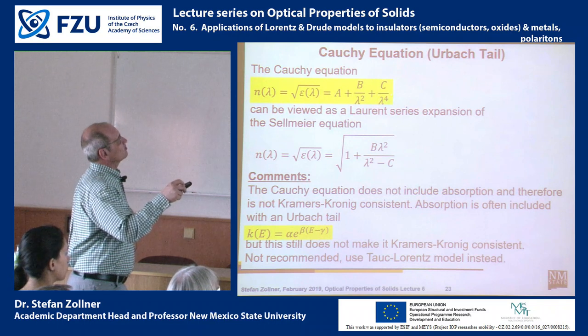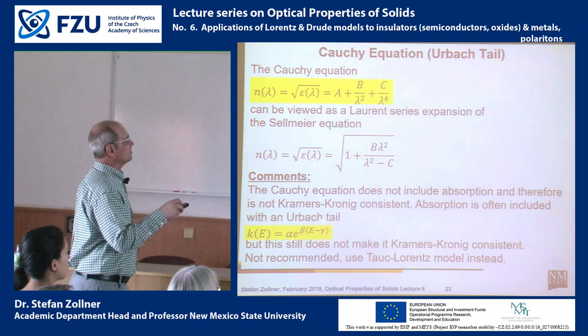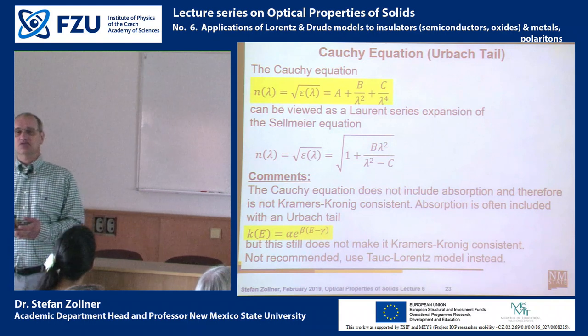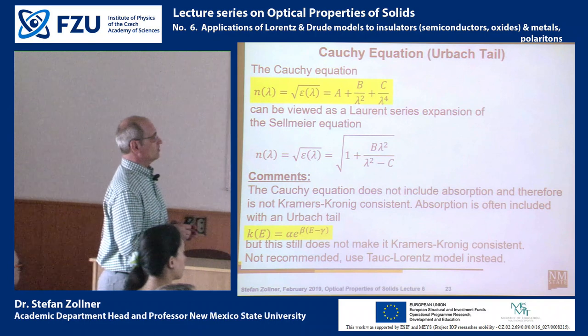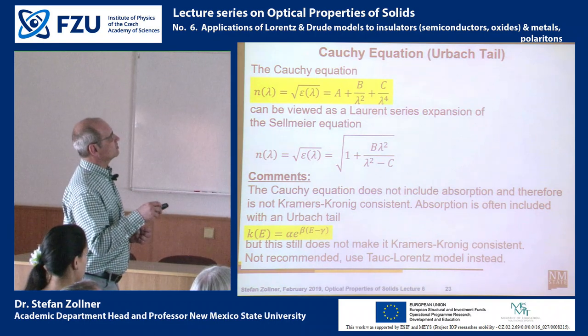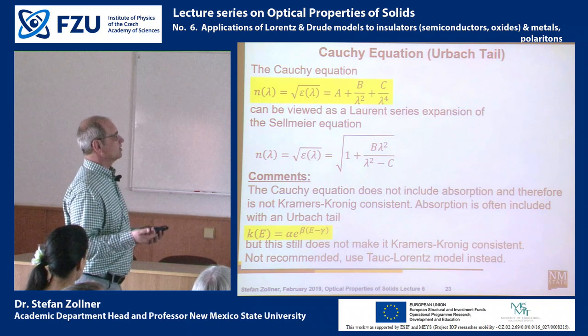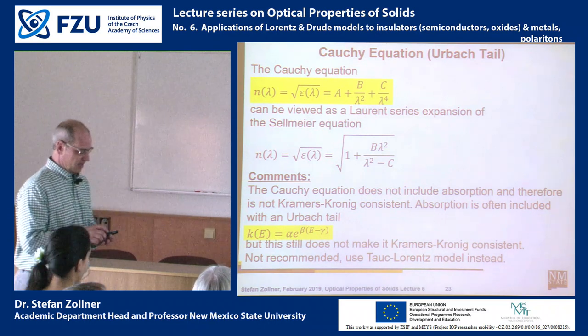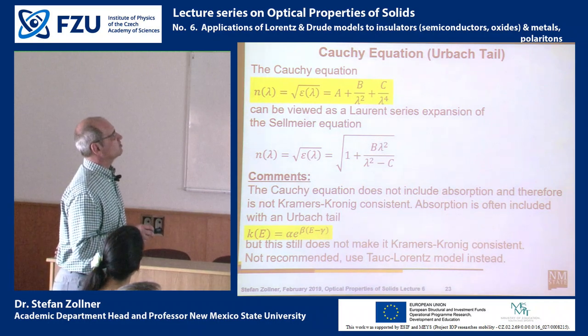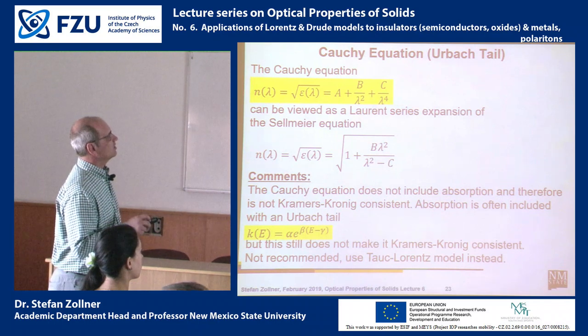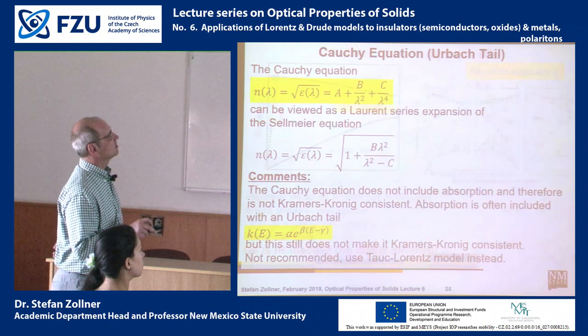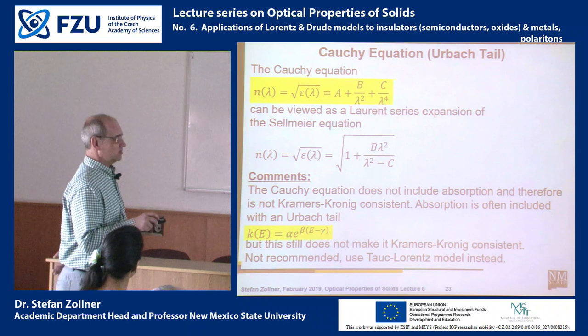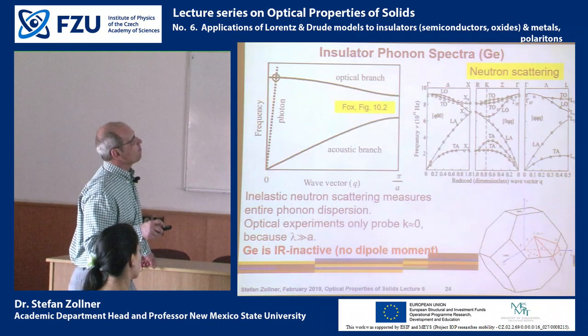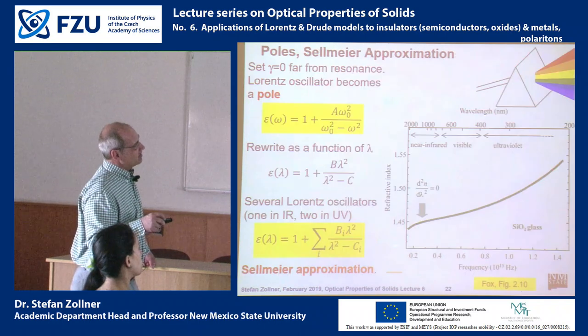But now if we look at the real part of the refractive index with the Cauchy equation and the extinction coefficient with an Urbach tail, this is certainly not Kramers-Kronig consistent. And therefore, I really do not recommend that anyone should use this Cauchy-Urbach model, even though it's simple, it has a small number of parameters, but the physics is just so wrong that you don't know what conclusions to draw from such an expansion. So instead of the Cauchy equation with an Urbach tail, it is much more common and much more physical to use a Tauc-Lorentz model instead. Maybe I will show you some examples for that later, but I don't have any examples here today. So there are a variety of models to describe the dispersion of insulators.